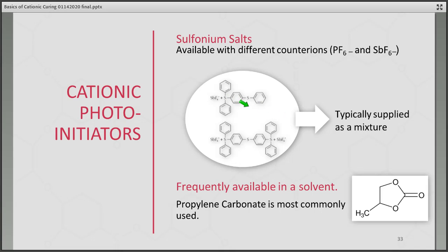They're available as a solid, as you could expect when you look at the structure here, at that molecular weight and overall structure. They're going to be more of a powder. However, it's easier to use liquids. So I believe most of the suppliers of the initiators also make them available in a solvent, and propylene carbonate, as we have a structure here, is most commonly used. So that it doesn't affect the overall reaction. So you usually see these as a liquid and as a mixture of components.